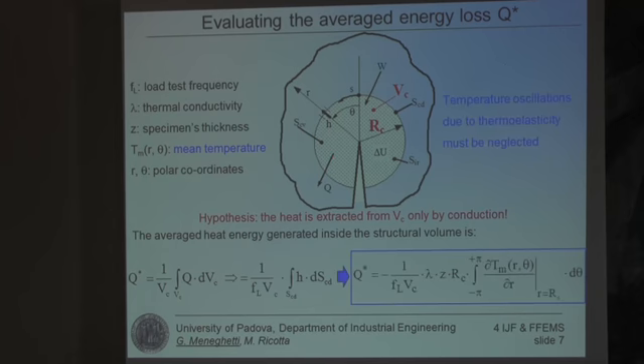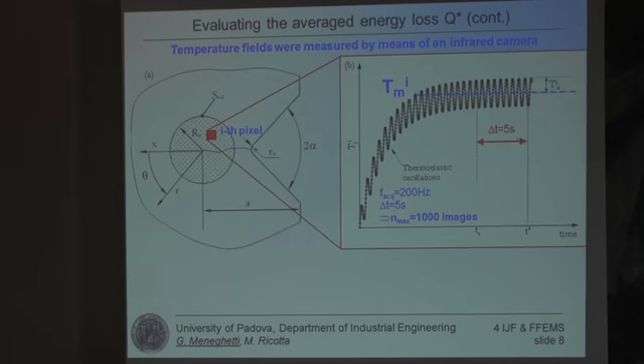This means that we need to evaluate the thermal field in polar coordinates, and we have to evaluate the temperature gradient exactly along the boundary of the structural volume. But when we perform such measurements in the laboratory, of course the mean temperature increase due to heat dissipation has another contribution, which is the thermoelastic temperature oscillation superimposed to the mean temperature increase. So what we typically measure in the laboratory is a signal like this.